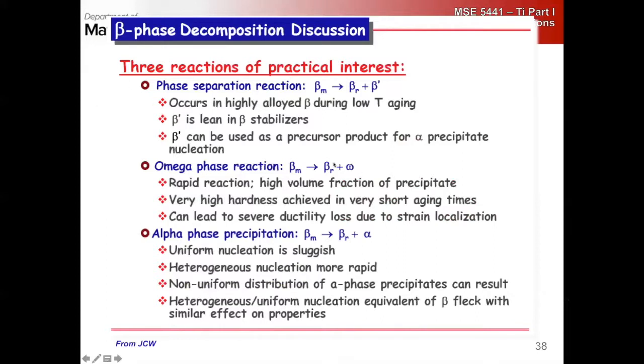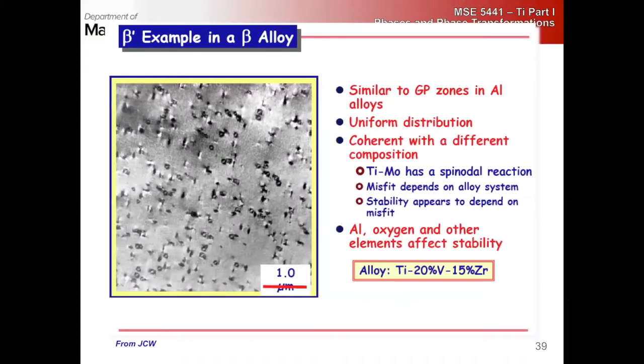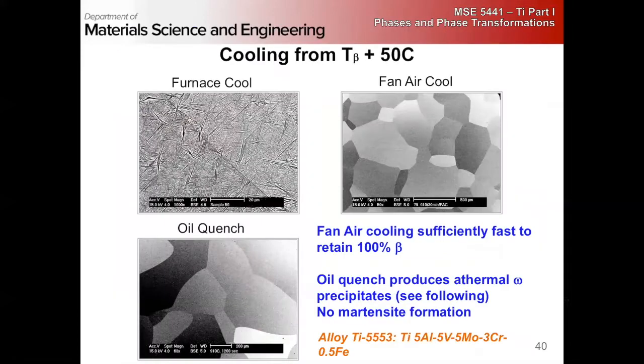Especially the omega phase formation, right, can happen in very short aging times when you have a very high dislocation density, right? So this was the beta prime. We talked about how this is very similar to GP zones, and it can either happen by spinodal or homogeneous or heterogeneous nucleation routes. Right, just an example.